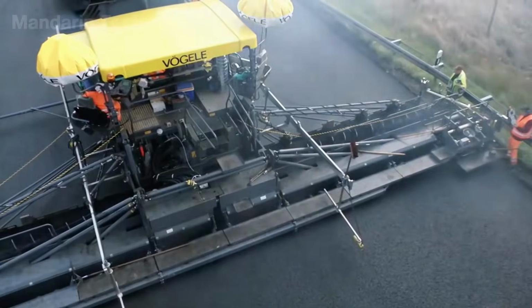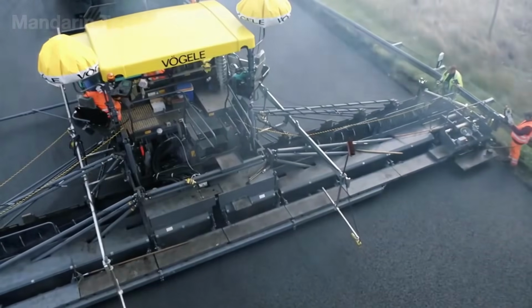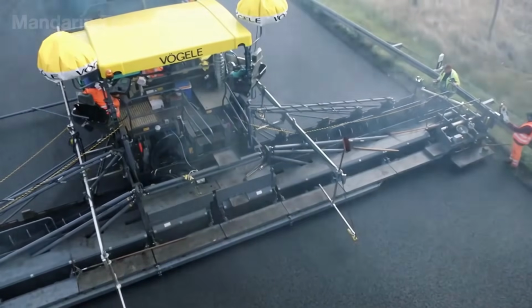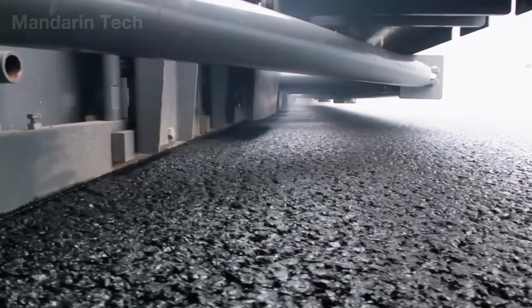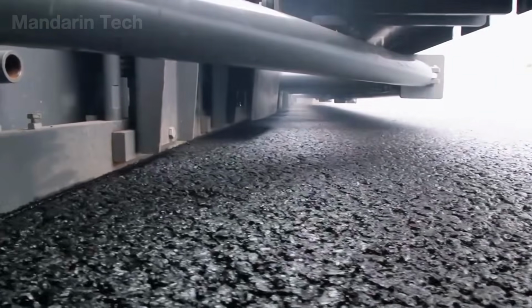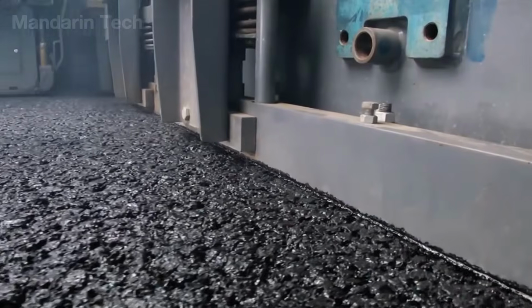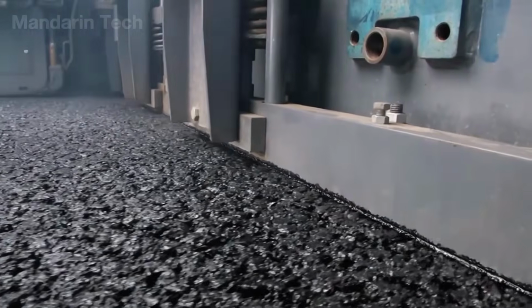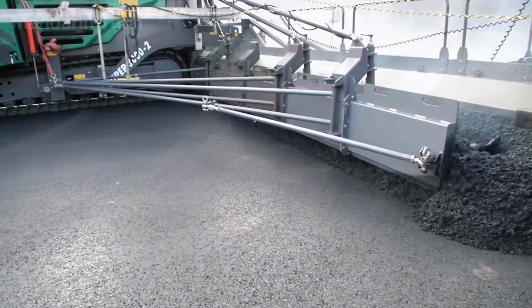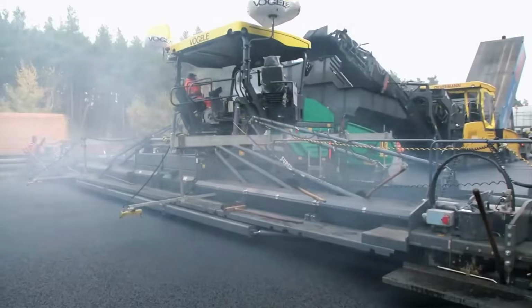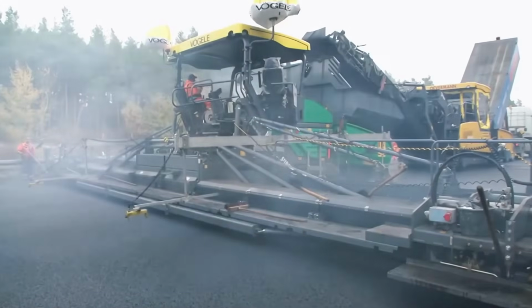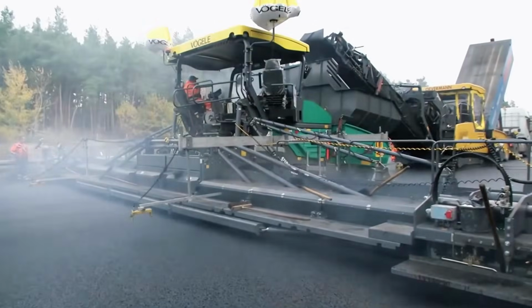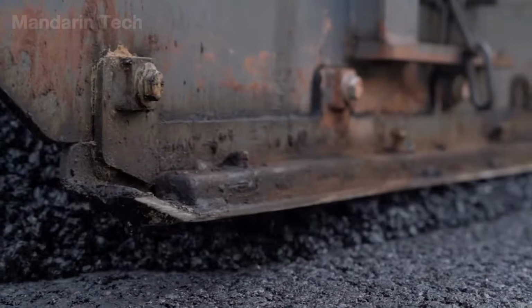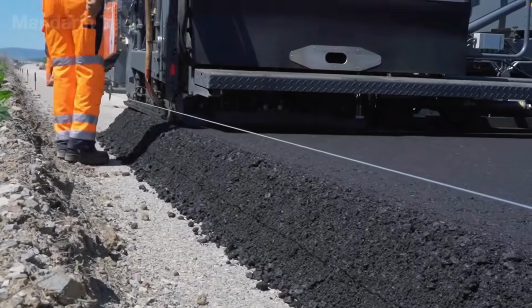The real magic happens at the screed, the vibrating, tamping, and pressing unit at the rear, which can achieve 85 to 92% compaction while the asphalt is still extremely hot. This allows the layer to be shaped, compressed, and smoothed in a single pass. This method is especially effective for the surface coarse or stone mastic asphalt, which is only about 2 to 3 centimeters thick and cools very quickly.